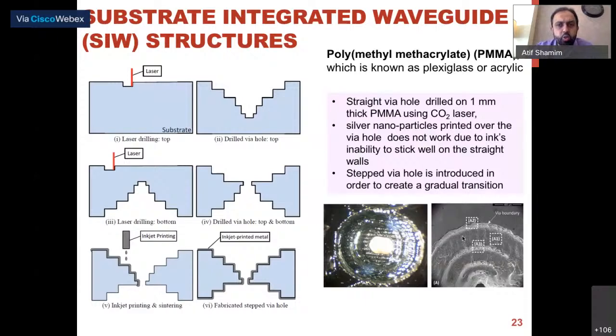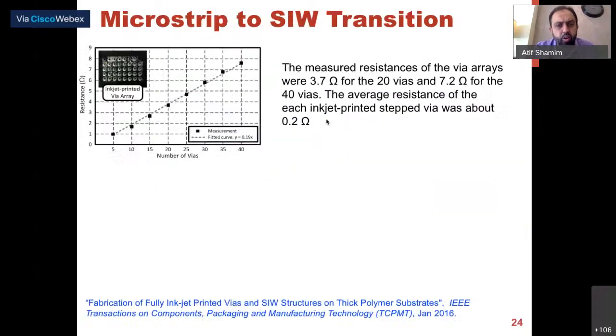And this is just showing that we have almost 0.2 ohm of resistance for one via, which was great, quite matching to the PCB based vias. Now we created a SIW structure. This was just a microstrip to SIW waveguide transition, but later on we also did some work on antennas and filters, and this worked very well. So you could create vias through printing, you could create your whole structure through printing, and it works well basically.